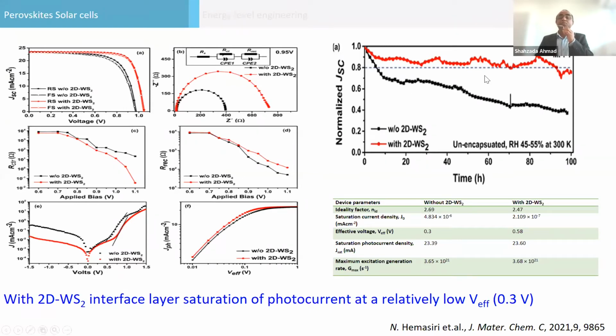And our aim was more to increase the stability, which you can see here, maximum power point tracking for 1,000 hours, 2,000 hours. It should improve performance compared to the control device without any 2D materials. So the 2D materials are very good, and they not only increase the stability, but also align the energetic levels. And by aligning the energetic levels, we can increase the voltage significantly. And also we found that the photocurrent became more saturated at very low voltage, at 300 millivolt, if you place the 2D layer.